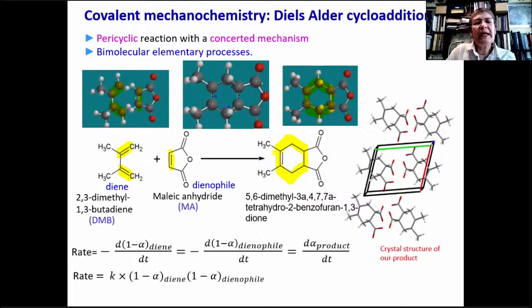So we know that our product is the product of a Diels Alder cycloaddition because we have the crystal structure. The maleic anhydride has hydrolyzed, so then we have this. We don't have the anhydride. We have 2 carboxylic acid groups, but the 6-carbon ring has been formed, indicating a Diels Alder cycloaddition.